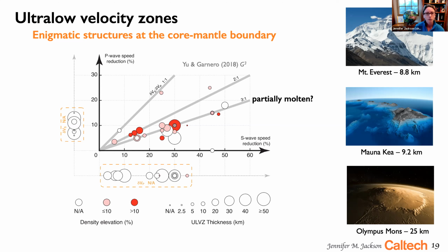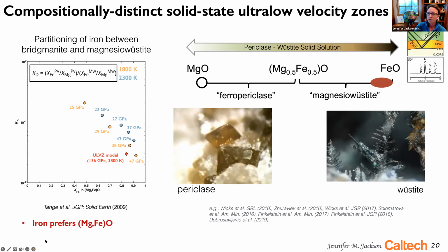Some of these ratios include the nominal 3:1 ratio, which has often been invoked as a partial melt hypothesis. But in many of these studies, this ratio is fixed in the seismic analyses, usually measuring one phase or another, the P wave or the S wave, rarely both. So we're going to hypothesize what these ultra-low velocity zones could be made of. From iron partitioning studies that have investigated coexisting silicates with oxides, iron strongly prefers the oxide. This led me to hypothesize that some of these ultra-low velocity zones could contain an iron-rich oxide.